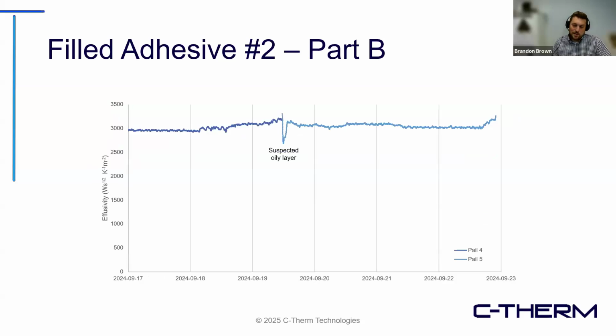Yep. So zooming in, this is just at the end of pail 4 and just at the start of pail 5. Here, instead of pail fill, the x-axis now represents time as it was processed. So you can see how it relates pail 4 and pail 5. It appears that right at the start of pail 5, there's just over a 10% dip off nominal, and you can still see the increase in effusivity at the end. Based on what we've seen from a few slides ago, I suspect this pail may have suffered from some settling and may have had a small oily layer, silicone oily layer on top.